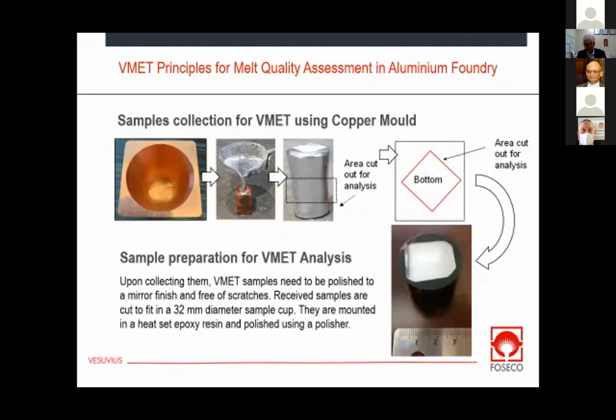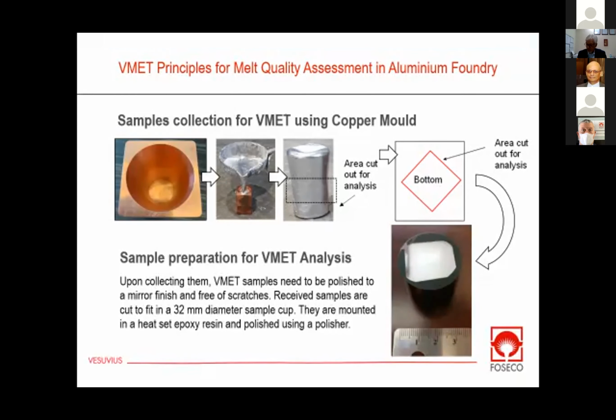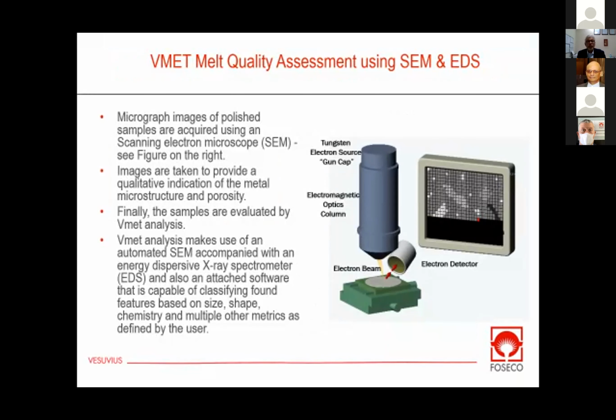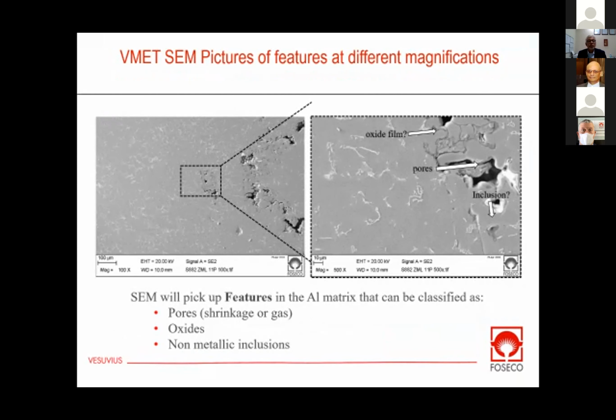We take a sample from a melting furnace, from a ladle, from a casting furnace, from a crucible, and then we section the sample, we polish it as you see here, and then we use our SEM and EDS to analyze. Basically what we are doing here is we're able to look at the structure with a scanning electron microscope, and the EDS is a spectrometer that can analyze the chemical nature of the features.